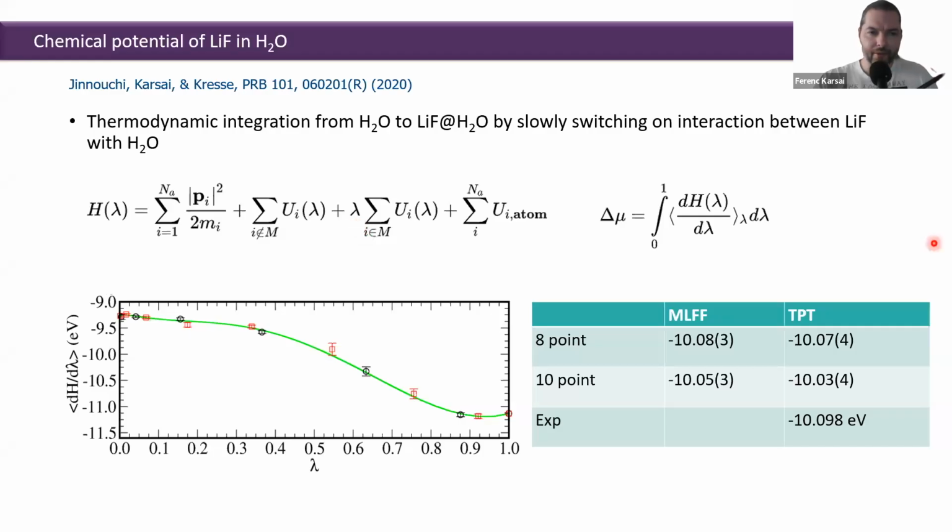Then by integrating this coupling parameter from the non-interacting to the fully interacting system, we can get the chemical potential. So we use this to slowly switch on the interactions of lithium fluoride put into a box of H2O, so lithium fluoride in liquid H2O.